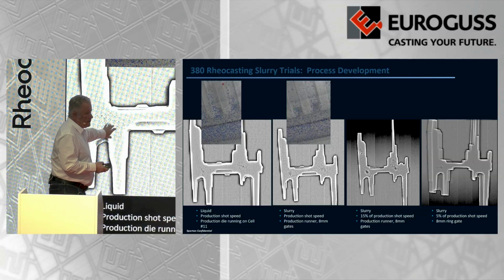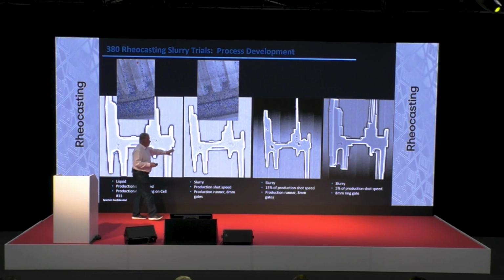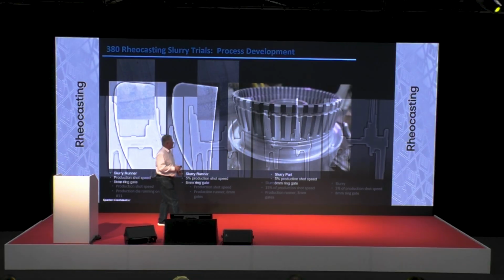So this is a production part here today. When we first tried to use slurry and shoot it using exactly the same shot speed, only very, very minor differences, slight improvement. Then we tried slowing the shot speed down to about 15%, and this looks terrible. It certainly did when we cut it apart. And as we developed that further, we found that we go a little bit slower, but significantly open up and go to a single ring gate, so we get a nice laminar flow through the tool. We've got a much cleaner part. So you can see a couple of little bits of shrink, but that's more sponge than it is anything else, and we're going to go a little bit further than that in our next trial.